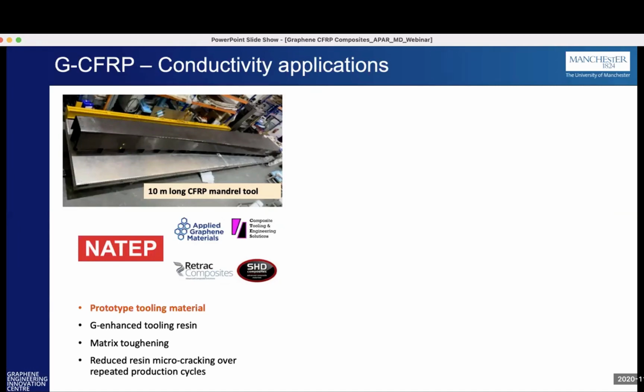So what these guys did at Applied Graphene and Composite Testing & Engineering Solutions, Retrac Composites, SHD, they developed a graphene enhanced prepreg, which was used just as a surface ply and used in areas where it was required. And what the graphene did was toughen the matrix, and that reduced the actual microcracking over the repeated cycles, so it extended the tool's life cycle. And in fact, I think that tool is still in service and hasn't had to be replaced as yet. So the costs have been driven down, and the customers using those tools are now very happy.